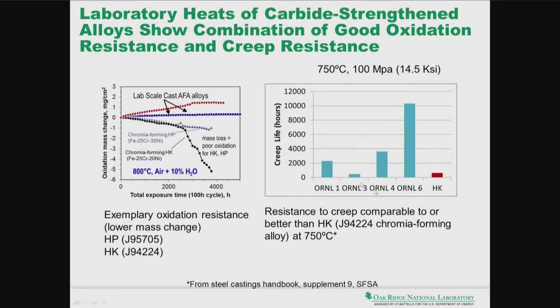On the creep side, these are experiments done at 750 C at 100 megapascals, and you can see that the HK alloy lifetime would be somewhere here, a couple of 100 hours perhaps, and we have lifetimes going up to 10,000 hours under similar conditions. So the alloys not only have good oxidation resistance, but also have good creep resistance.